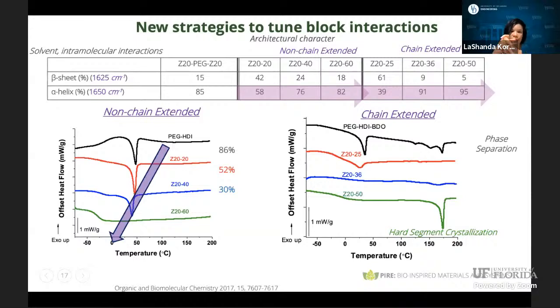Now, a couple of things emerge with the non-chain extended systems. Once you place it into this polymeric framework, you actually have a decrease initially. So at 20 weight percent, you have a decrease in the alpha helical content. By the time you reach about 60 weight percent, you've recovered to close to the original value of your starting soft block system. In the chain extended system, you have a similar picture. You have 39%, much lower than that of the pure soft segment, but you can see quickly at 36% and then at close to 60%, you actually are able to surpass what you have for your pure soft block. And we believe that is due to differences in phase associated behavior.